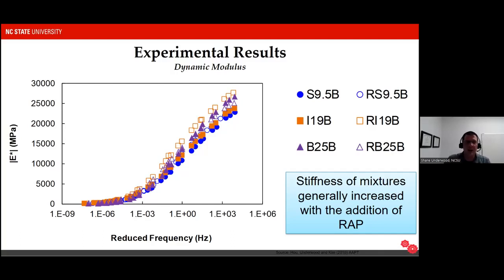Okay, there we go. When you look at these graphs, you'll notice that the RAP materials shown here in the unfilled symbols compared to their equivalent filled symbols are higher in modulus. So what this shows us is that when you add RAP materials to the asphalt mixture, the stiffness increases. This is not necessarily a bad thing. And in fact, for rutting resistance, this might be a very good thing because it tells us that our pavement would be less likely to deform under a prescribed load.